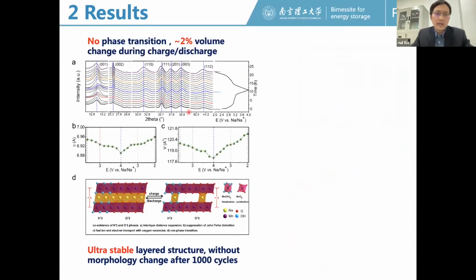After that, we try to investigate the structure evolution during the charge and the discharge. So we did this in situ synchrotron XRD, and we can find that during the charge and the discharge, this material has no phase transition, and the volume change during this charge and discharge is only 2%. Which indicates the structure is highly stable during the charge and discharge because the volume change is very small. And I mean, the strain during the charge and discharge should also be very small because of the small volume change.